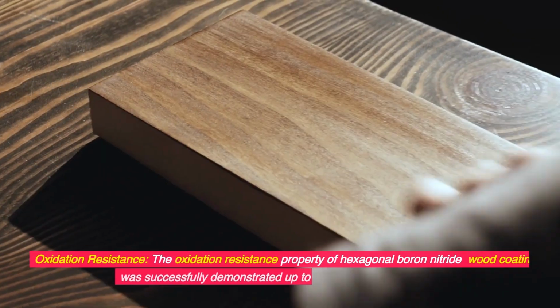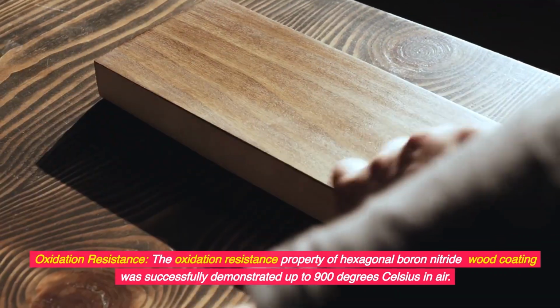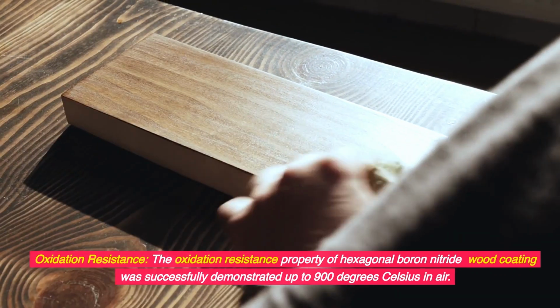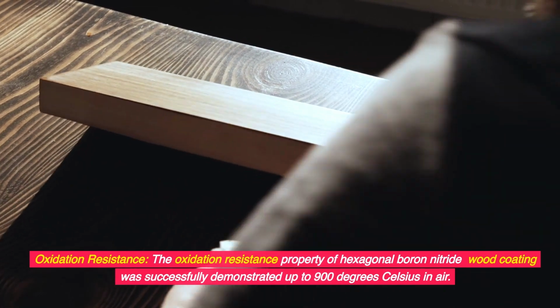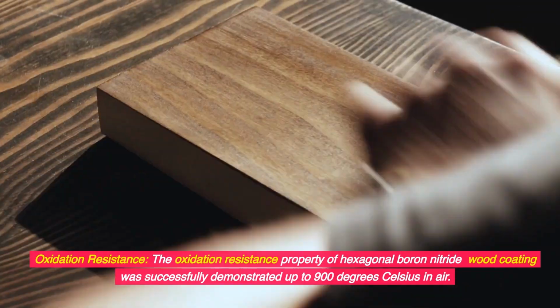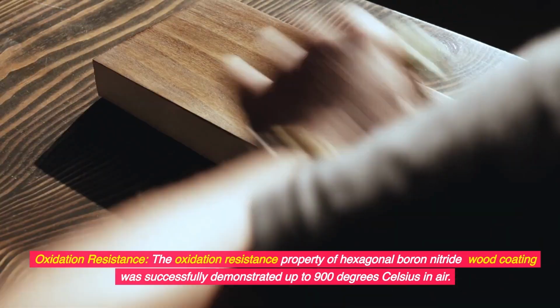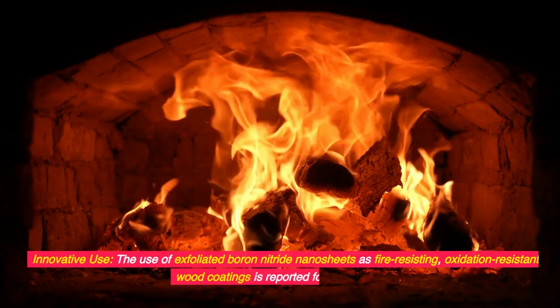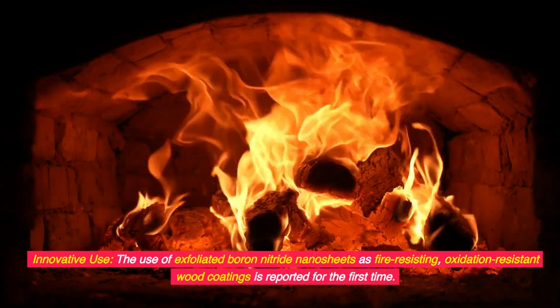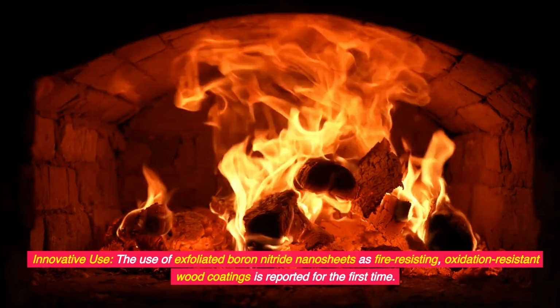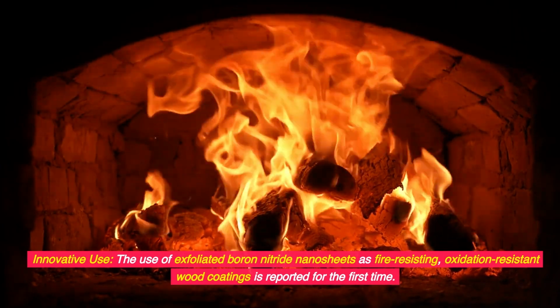Oxidation resistance: the oxidation resistance property of the hexagonal boron nitride wood coating was successfully demonstrated up to 900 degrees Celsius in air. Innovative use: the use of exfoliated boron nitride nanosheets as fire-resisting, oxidation-resistant wood coatings is reported for the first time.